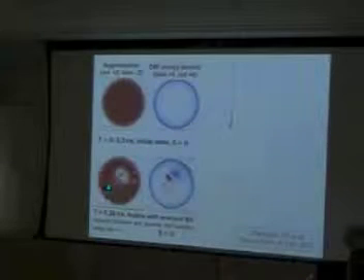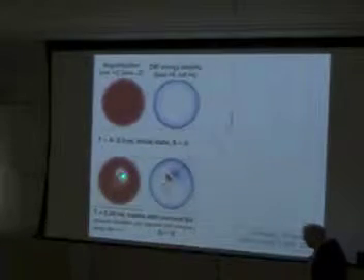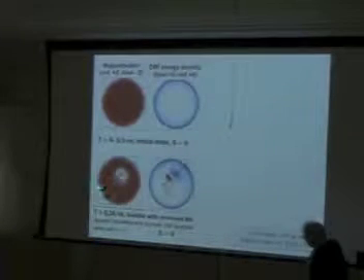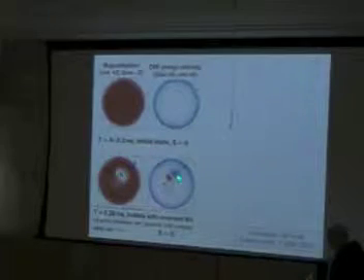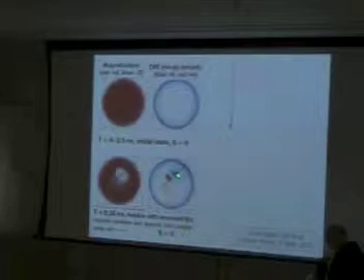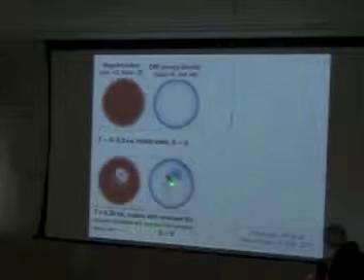A bubble, but this is not a skyrmion. The first stage is not a skyrmion. It's a bubble. You can see that if you look at the rotation of the spin, the rotation is clockwise here, and then anti-clockwise on this side when one goes along this line. If you look at the DMI energy, on this side there is a negative energy whose chirality agrees with the sign of the DMI, and on this side it disagrees and increases the energy. So it is a bubble, a hard bubble.